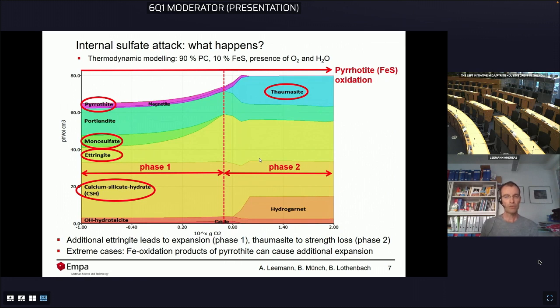Now, you put pyrrhotite on top of it. And going from the left to the right, you oxidize this pyrrhotite. This means sulfur is released into the concrete. And now please look at the green area represented by the monosulfate. When you release sulfur, the amount of monosulfate gets smaller and smaller until you reach the dashed line, okay? Ettringite is formed at the expense of monosulfate. And if you form ettringite in a hardened concrete, you will experience stress, expansion, and cracking.